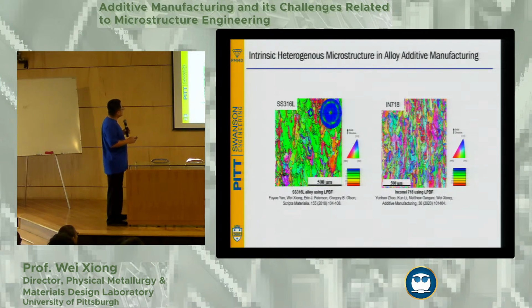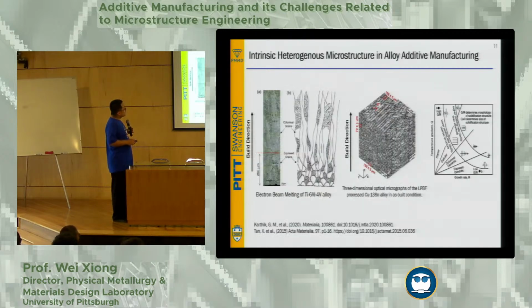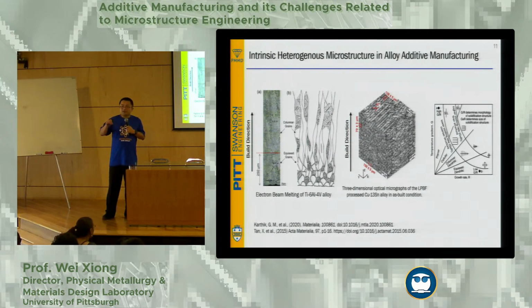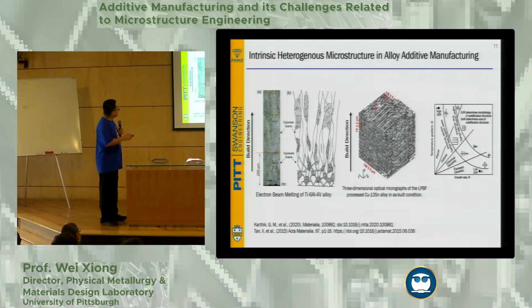This is another comparison, similar in nature. Since we're talking about heterogeneous material today, I introduced heterogeneous microstructure. You can see it's heterogeneous with both the 316 alloy and 718 alloys—in the printed microstructure, different directions show different morphology of the microstructure. This is because the melting behavior at each point is governed by the processing parameters. You have a strong thermal gradient along the build direction, therefore you can more easily see this columnar structure.